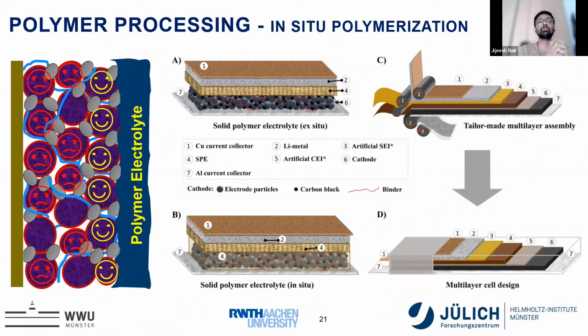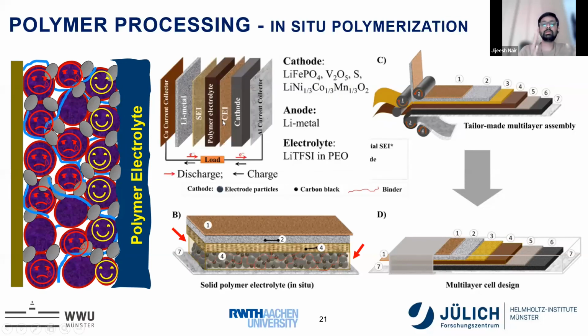So instead of going for one polymer, one salt system, you can develop multi-layers of electrolytes with different thickness. And these electrolytes can be engineered in such a way that they can be target specific. Maybe you will have an electrolyte that is closer to the cathode, so it will be stable against the cathode, whereas it may not be stable against the anode. Then you develop another layer, an interface layer, which is again a polymer electrolyte, which can have very good interaction with the lithium metal. And then a center layer, which can have another property. So you can really tune according to your need how you want to design your polymer.